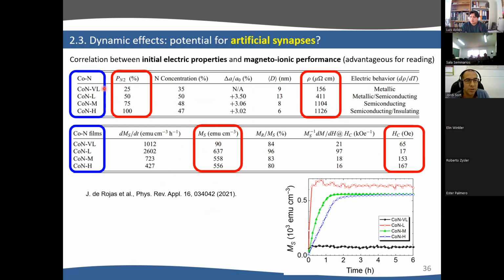If you change the nitrogen partial pressure of the layers, when we grow the layers by sputtering, you can see that you can modulate the resistivity. And depending on the type of sample and what resistivity value we have, there is a different magneto-ionic response. This is something we need to further investigate in situ. We want to measure in situ the resistivity of the layers, how it changes when we apply voltage. But for the time being, this correlation between electric and magnetic properties exists here, which is good for neuromorphic, especially for synaptic functionalities.